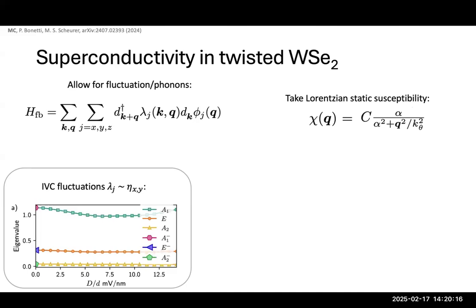And so for IVC fluctuations, what we find is that for a value of alpha roughly 1, this A1 state wins, and it's a state which connects in the limit of zero displacement field to the odd momentum version of this state. So this is a state which we generically expect to be nodal.